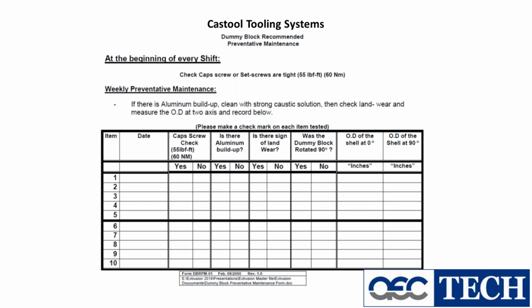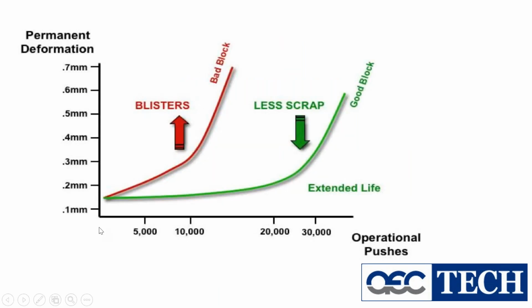So it goes back to the diminished life of the block, and as its life is diminishing, how does it contribute to unscheduled downtime, recovery, and all those types of things. So when we look at it on a chart in sizes of permanent deformation, if we start to chart the OD of the dummy block as we take it off, and we look at 1 millimeter of deformation, 2, 3, 4, 5, we'll find that when we get to a certain size, say at 3 millimeters on our block, you'll start to see back end blisters happening in the block.